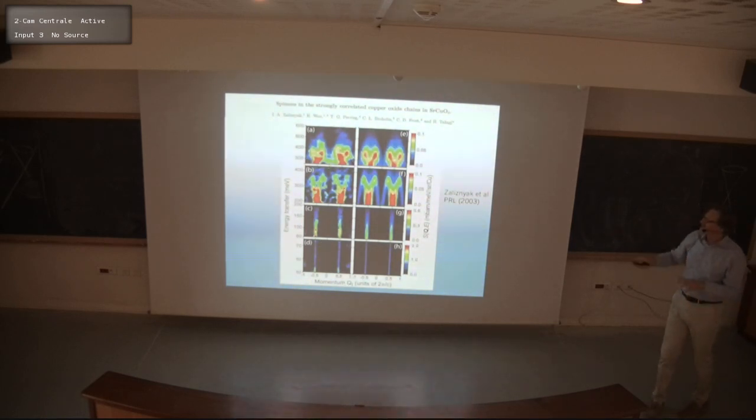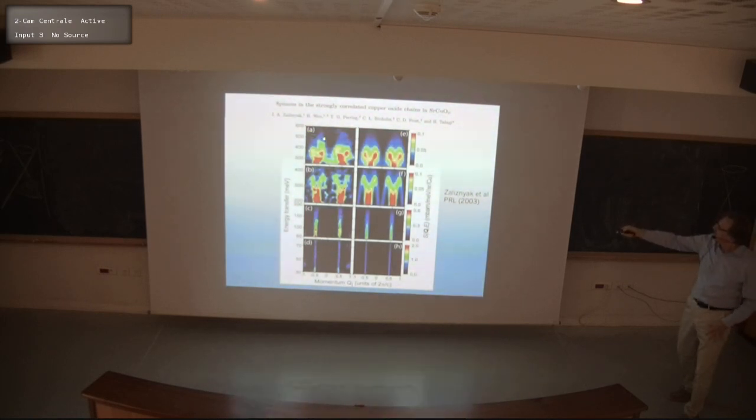And just in terms of the scattering, it's pretty amazing for us in doing the experiments. Over all of the energy range up to maybe 100 millielectron volts, it almost looks like a completely sharp ridge pinned right at the wave vector transfer corresponding to the antiferromagnetic wave vector. But it really extends up and then eventually broadens out, and then it has this continuum scattering. And in these comparisons between the experiment and theory, the statistics is not so great here, but it's pretty good here, and it really seems to work quite well.